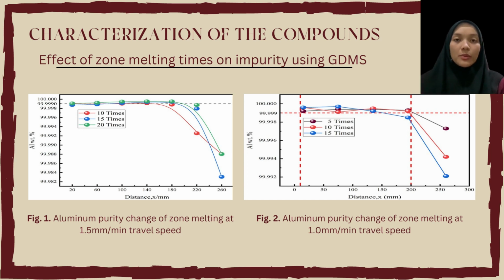At travel speed 1.5 mm per minute, the aluminium content in the same position of the product increases with an increase in the number of zone melting times. At travel speed 1.0 mm per minute, the purity of aluminium is greatly reduced in the tail after the impurity accumulates and is not up to the national standard. In this context, the tail should be removed to reduce the cost.